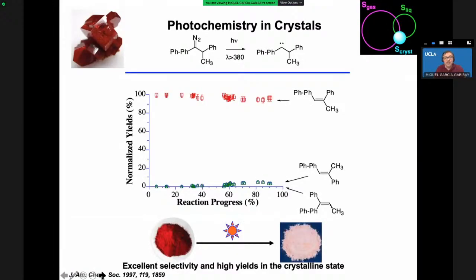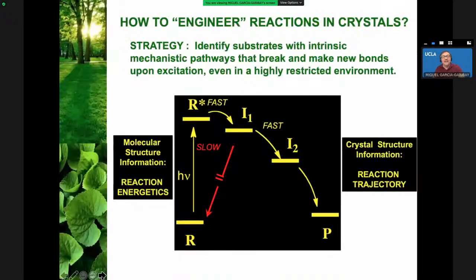So you can see here how a nice fine powder changes before and after reaction. And what you can see is that as a function of reaction progress, the selectivity of the reaction remains very high. We have excellent selectivity and high yields in the crystalline state. So the question is, how do you go about designing reactions in crystals? So what crystals are going to react and what crystals are not going to react? So this is the strategy that we use in my research group, and I invite you to test it.